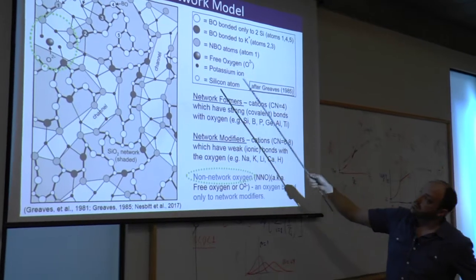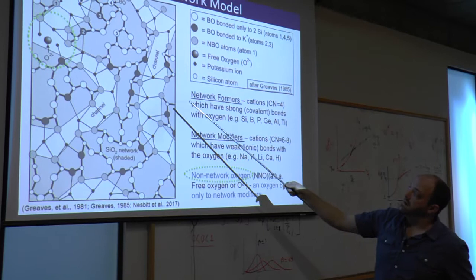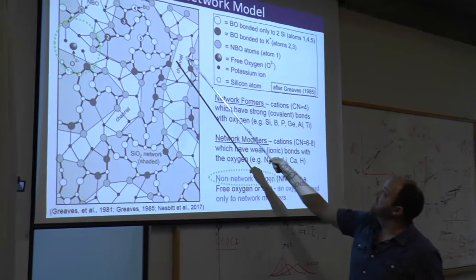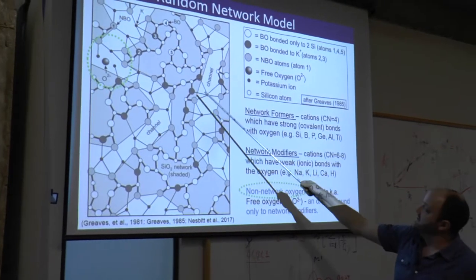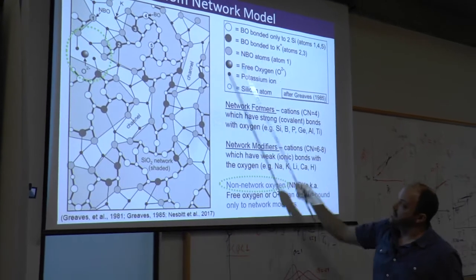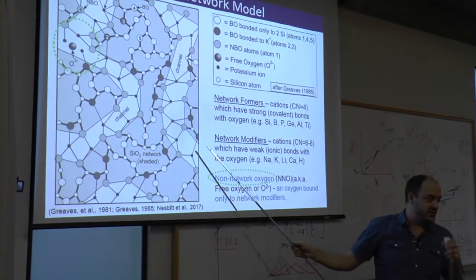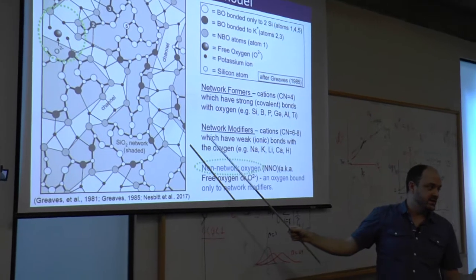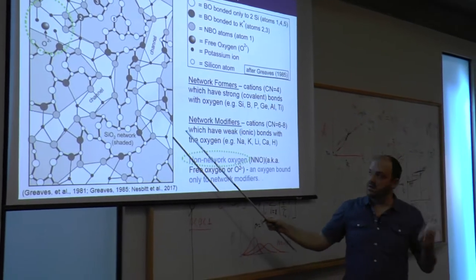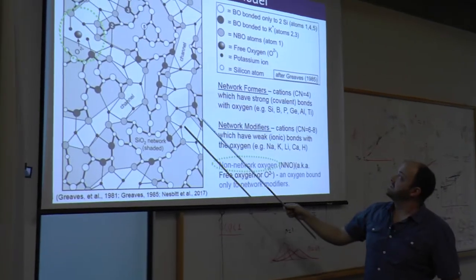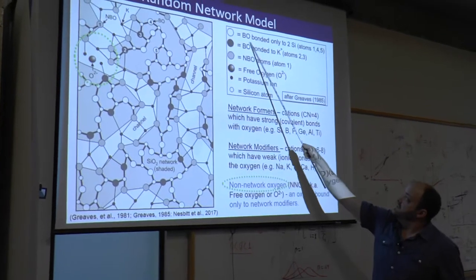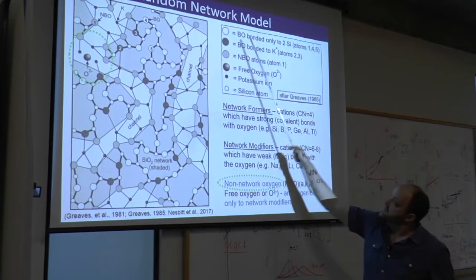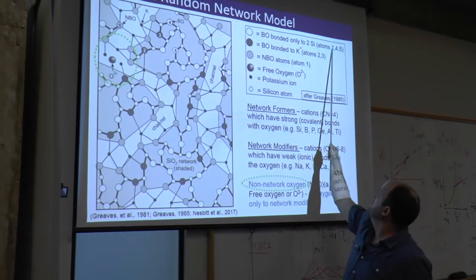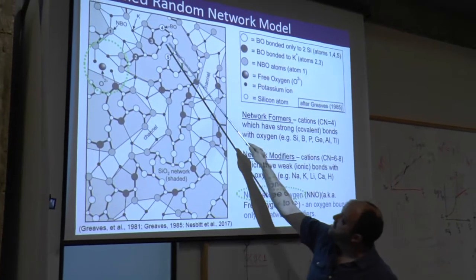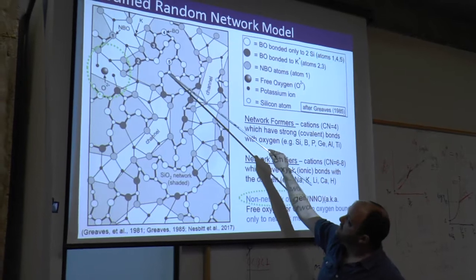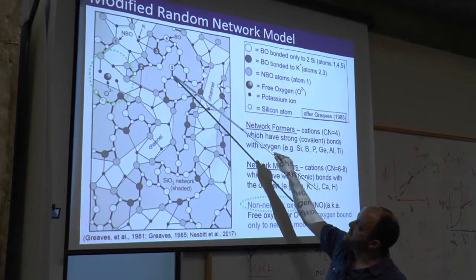So let's go through in a little bit of detail what is actually going on in this photograph of this model. The first thing you have to remember about all these is that they're 2D and not 3D. So we're missing a dimension of reality, and you have to keep that in mind. And sometimes it's pretty difficult. If we look first at the bridging oxygens, some bridging oxygens, for example, 1, 4, and 5, so here's 5, this guy is only bound to other silicon atoms.